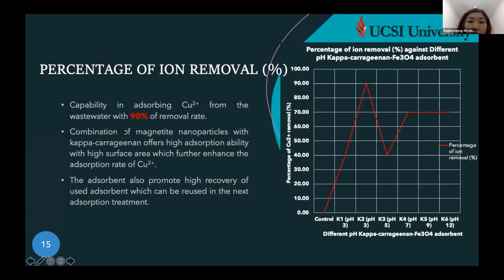Next, we will move to the percentage of copper ion removal. The Kappa-carrageenan iron oxide adsorbent at pH 3 removed the copper ion with a 90% removal rate, which further proves that this developed adsorbent has high surface area that can enhance the copper ion adsorption rate. Also, this adsorbent has a high recovery rate, which can be reused in the next adsorption treatment. However, further research will be carried out to recollect the adsorbent and Kappa-carrageenan from the wastewater for desorption treatment.